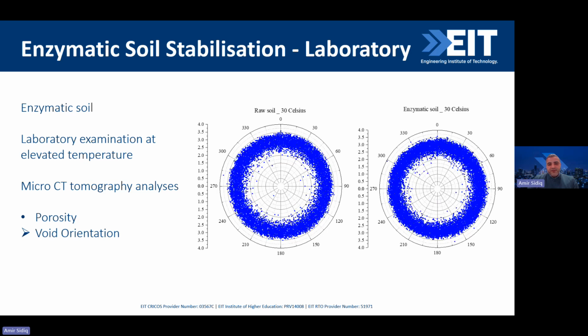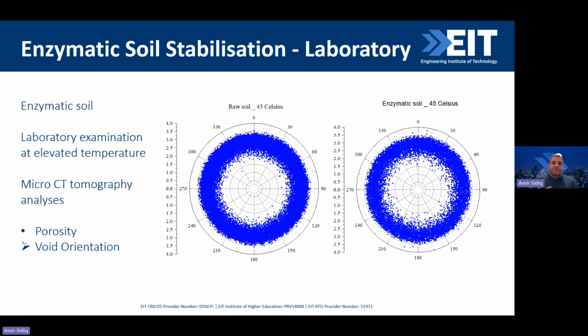Then at 30 degrees, we can see the number of pores within the raw material is increasing. But then for the enzyme, it's still constant. Again, it's controlling the actual pores. At 45 degrees, the line is becoming thicker. And for the enzyme, the amount of pores is starting to become lesser. But then for the raw, it's actually increasing significantly, because we can see it's solid, in some cases solid blue, which is full of voids compared to the enzymatic.